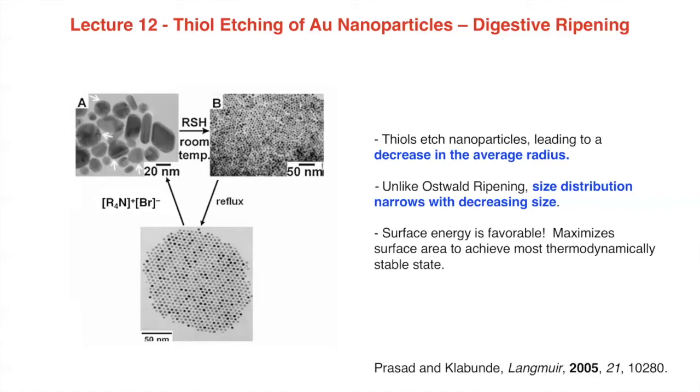And so the system is trying to maximize surface area, dictated by a certain ratio of ligands to metal. And if you knock those ligands off using a different surfactant, that can go away. Okay, so there's something special about gold and thiols, which should be familiar to everybody, I would imagine. And in this example, that plays out by leading to this narrow distribution. That's a thermodynamic product, okay? And that is unusual and interesting.